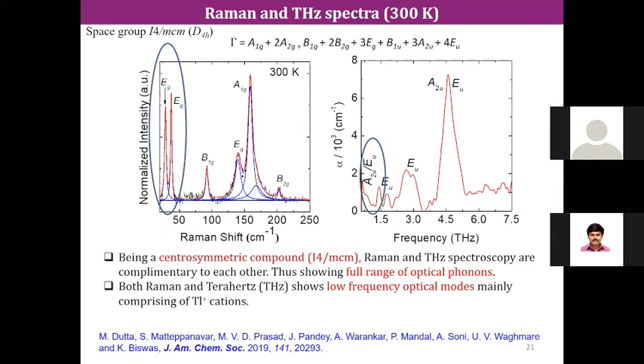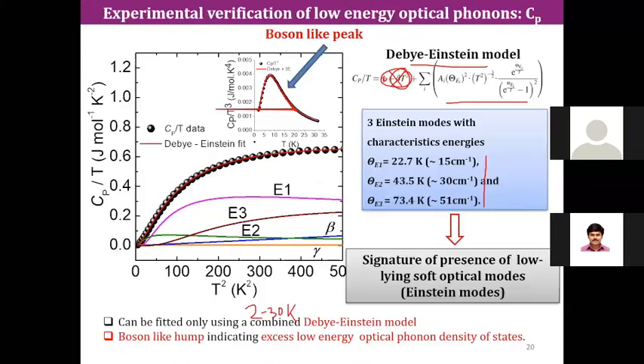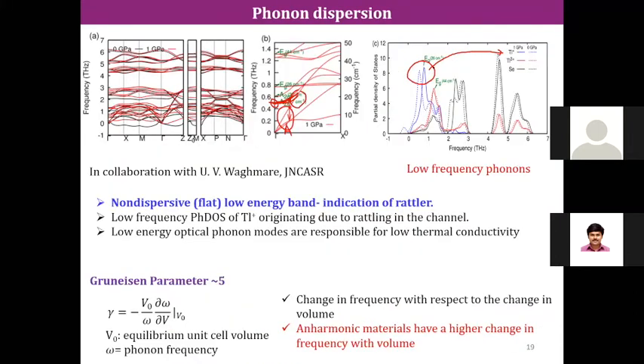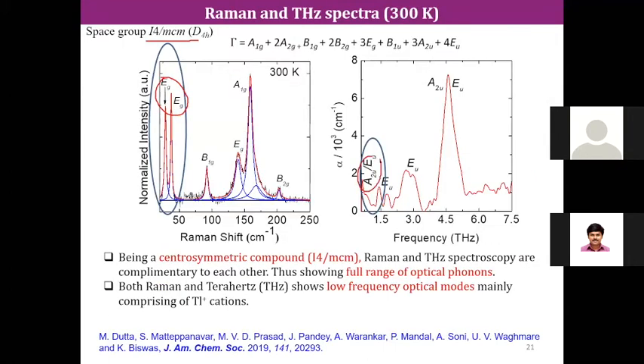Okay, so now, as I told you in the beginning, optical phonon modes can be seen by Raman, terahertz, or IR spectroscopy. So can we see these rattler modes directly by experiment? Actually, yes. Fortunately, this compound has a centrosymmetric space group, so it will obey the mutual exclusion principle. That means some modes will be Raman active, some modes will be IR active. So we have done Raman first. You can see these Eg modes, which are predicted by theory as well as our chemical intuition. These modes can be seen now, and these are the rattler modes.